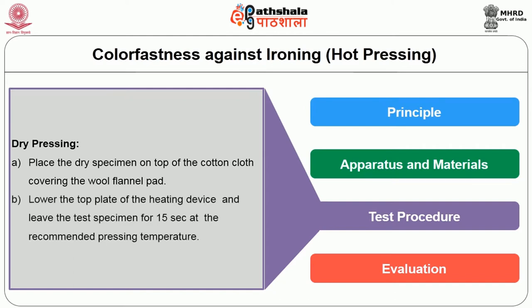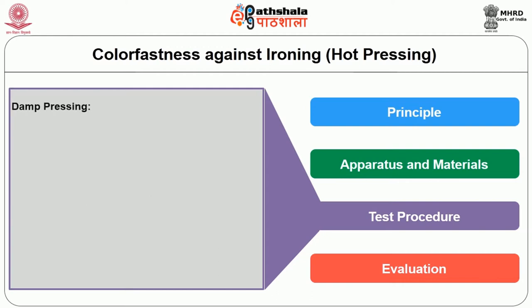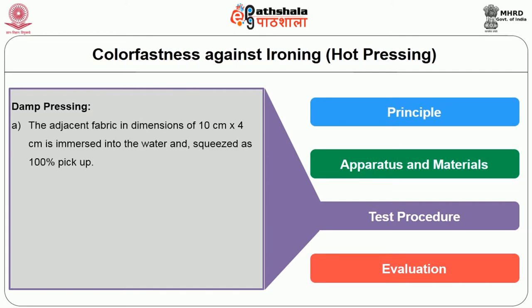Lower the top plate of the heating device and leave the test specimen for 15 seconds at the recommended pressing temperature. Damp pressing: here, adjacent cotton fabric in dimension of 10 cm by 4 cm is immersed into the water and squeezed to get 100% pickup.